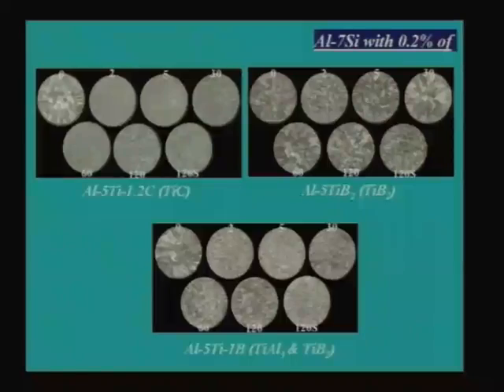So people want to study which kind of particle is very good as far as these poisoning alloys are concerned. I cannot say you do not use that kind of alloy, because aluminum silicon alloy has certain important applications. We cannot say do not use aluminum silicon alloy. The only way is either you do not grain refine it at all, which means you are not able to achieve the improvement in strength that you could have achieved by grain refinement, or you add a grain refiner where the particles do not get reacted by the silicon, where the particles are stronger, where the bonding between the two elements in the particle is much stronger than with silicon. One such example is TiC.